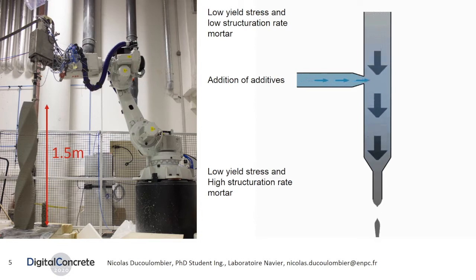But this measurement is really difficult to achieve, especially for high structuration rate materials needed for a fast fabrication of slender post-like structures. For instance, the one shown in the left picture was fabricated in 15 minutes. The high structuration rate is in this case provided by the addition of accelerator in the printing head. This high structuration rate prevents the use of existing rheological apparatus such as slump or squeezing tests, as the time needed to prepare the sample will lead to an important modification of the yield stress.